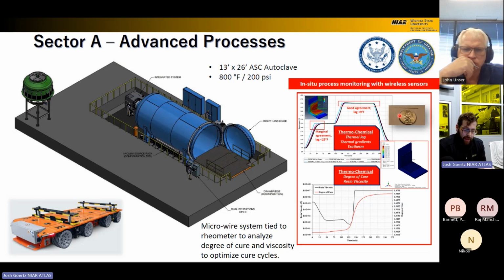And when you embed these sensors inside of the part, let's say there's more tool mass behind a certain region, or if that's the thickest part of the buildup, then we have these wireless sensors embedded in the part that's going through the autoclave cycle, and that temperature is fed directly into an external rheometer, where we have a stack of the exact same layup sequence, exact same batch of material, and then we can measure the degree of cure and the viscosity of the material by driving that sample to exactly the same temperature as what's inside the part. And what that allows you to do is fully optimize your autoclave cycle.